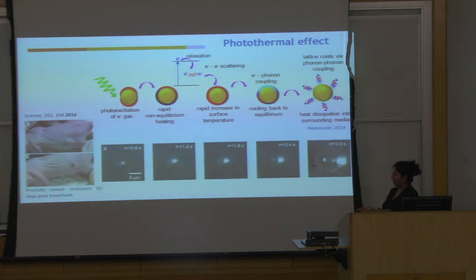If you don't like biological examples, here is one. What we are looking at is a gold nanoparticle in water. And here you can see a bubble of steam forming. It can actually boil water. It heats up so much by just shining light. Work like this was done by Naomi Halas. She found a way that you can use this as a method to sterilize equipment when you're out in the field. If you're in Africa and you need to do surgery and you have no source of fuel anywhere, you take your nanoparticles, you can boil water and sterilize things if you like. The photothermal effect is very strong. So that's what's happening here.